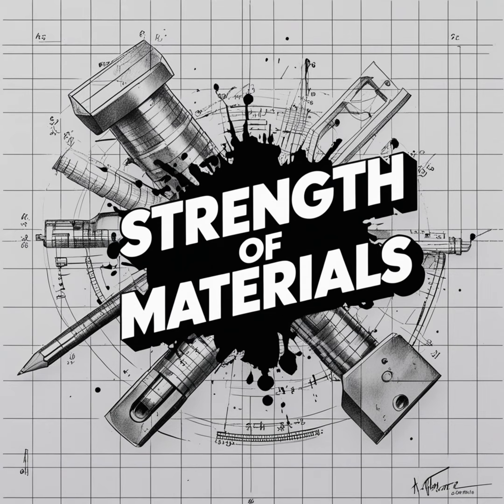So how do engineers actually use this wave data to predict when a bridge cable or an axle is going to snap? Like, how do they predict the future? They map it out using what is famously known as an SN curve. SN curve. Yeah. S stands for the applied stress amplitude, and N stands for the number of cycles to failure. You plot stress on the vertical axis and cycles on the horizontal axis. Okay, pretty straightforward. And because a part might survive 10 million cycles, the horizontal axis is logarithmic, just so we can fit it on a single piece of paper.